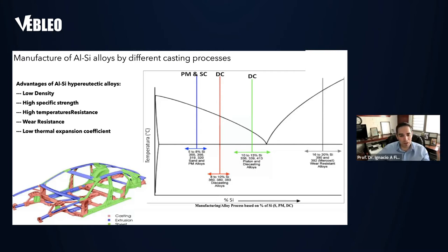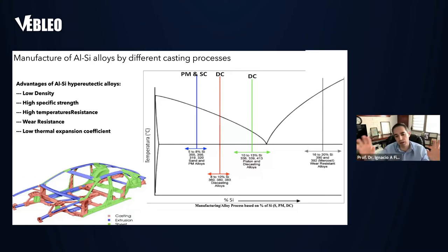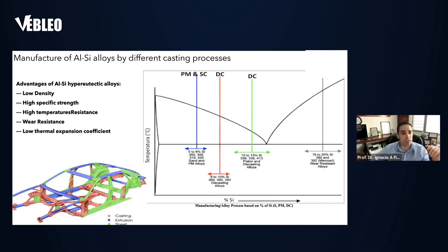This is basically the part of a car where the aluminum is employed and this is the process where they came from. Silicon is an important element which drops the viscosity of aluminum, so you're going to cast aluminum in some very narrow parts of a mold. You can fill them up completely by adding silicon. Silicon drops the viscosity drastically.